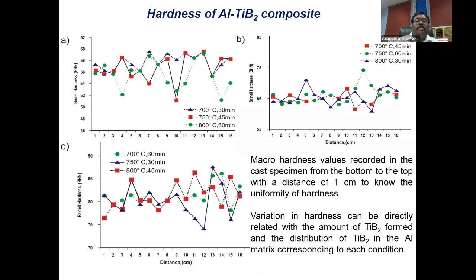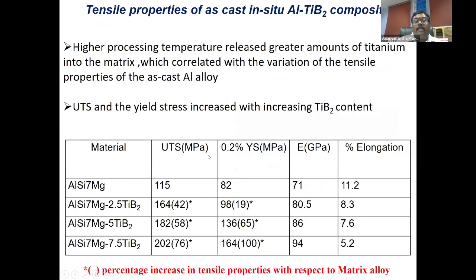With this, we can say that it gives a homogeneous distribution, which can be demonstrated by measuring the hardness along the length direction and across. Because the distribution is homogeneous, the hardness value measured anywhere on the surface shows a homogeneous value. There is also a greater improvement in the mechanical properties. One more interesting thing is that we could not notice any interface formation, because the reaction itself gives the particle and no further reaction occurs. So the particle directly contacts the matrix, and as a result it creates good bonding. The strength improved from the original 115 megapascal to 202 megapascal, which was a great achievement.